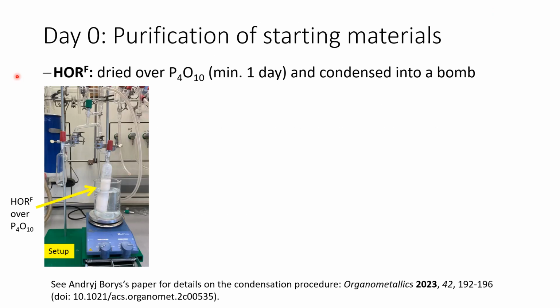So let's start with the purification of our starting materials. It is very important for the reaction to thoroughly dry our perfluorobutanol. As a drying agent, we use phosphorus pentoxide. To dry our alcohol, we fill the alcohol as well as the pentoxide into a storage vessel. This should be left to dry for at least 1 day, preferably a few days.